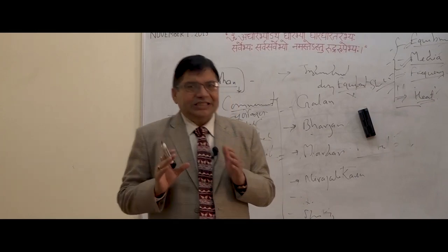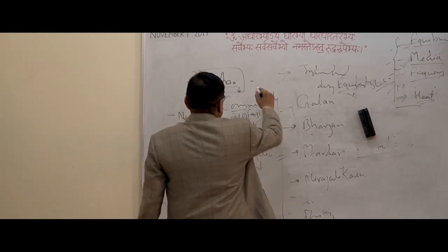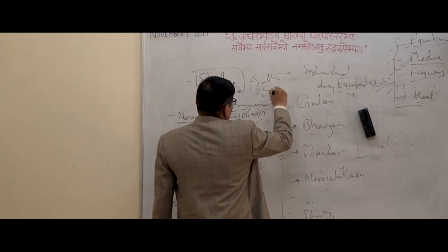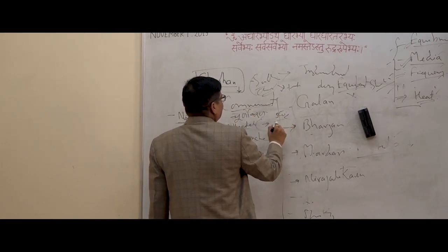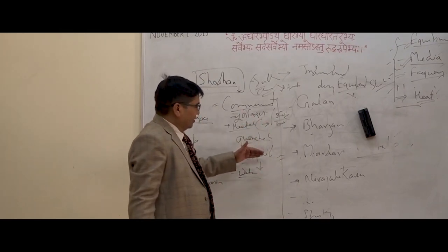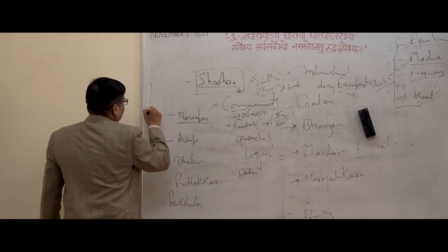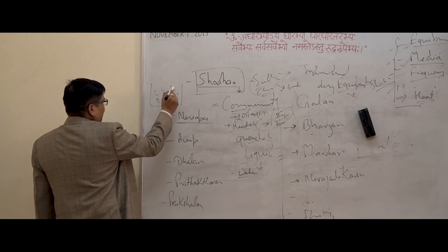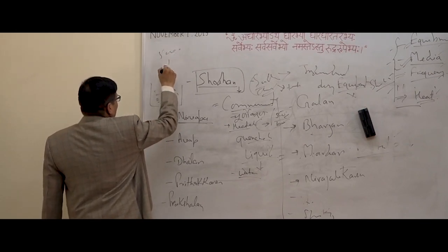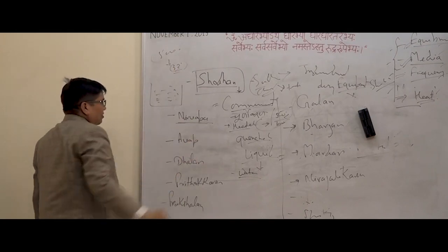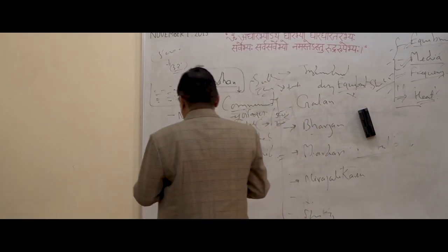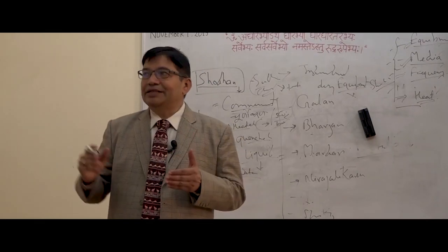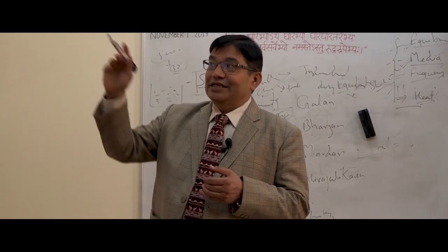The science behind it, the principle behind it, is the sudden change in temperature. If it is red hot, it is certainly touching 500-600 degrees centigrade, and then all of a sudden it is quenched in the media at room temperature. This sudden change from 500 to approximately 32 degrees centigrade is responsible for the breaking of the size. By this, the whole objective, the reduction in the particle size, took place by this method of Nirvap.